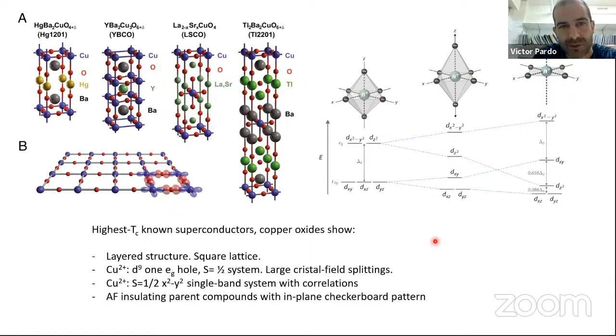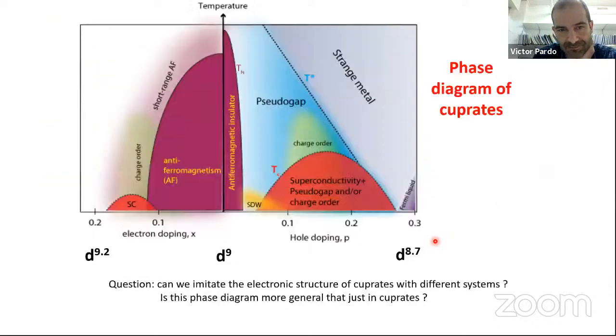So what one would like to understand is what other systems share some of these features and whether they are superconductors or not. This is more or less the phase diagram of the cuprates. As I said, you have the antiferromagnetic insulating phase at nominal d9 filling, and when you start doping it, when you start changing the electron count in the d band, you have a superconducting dome with a very high transition temperature. And here at this limit, you start having a more normal metal, maybe a Fermi liquid or maybe a strange metal, but certainly a metal.